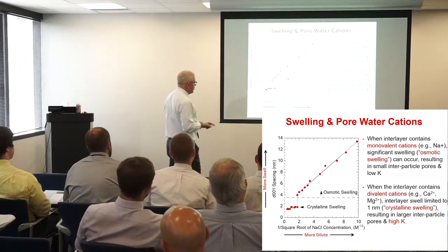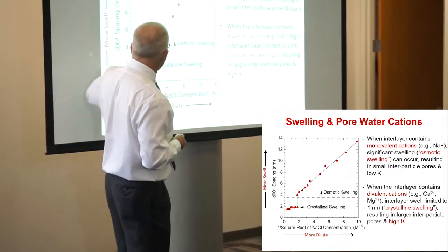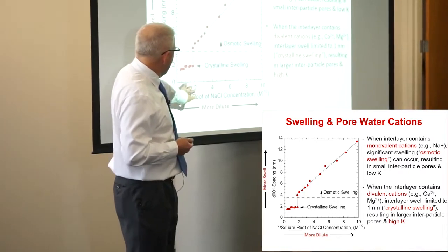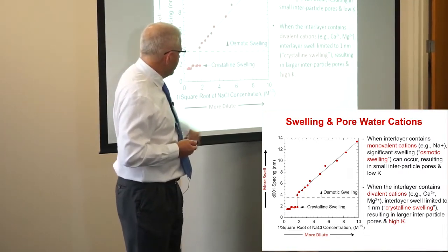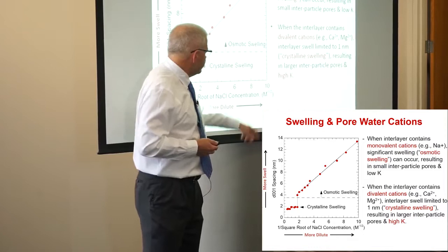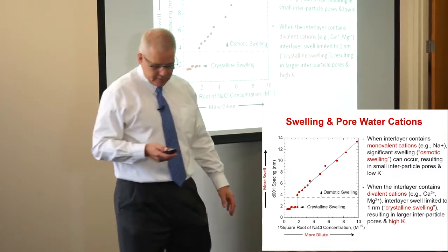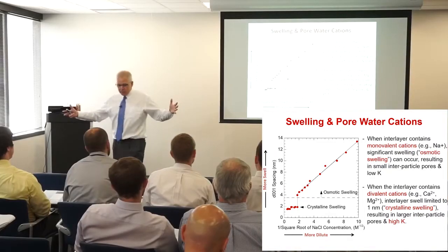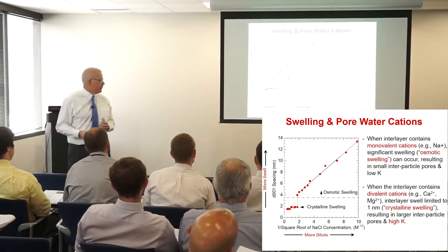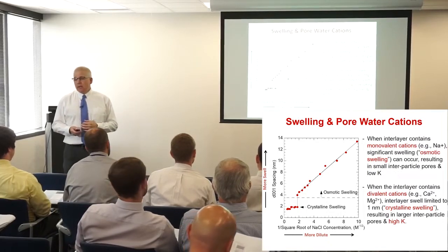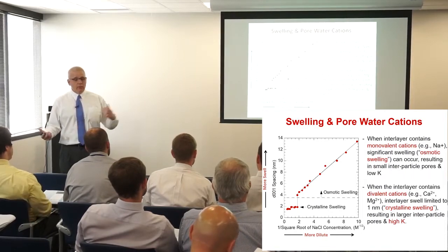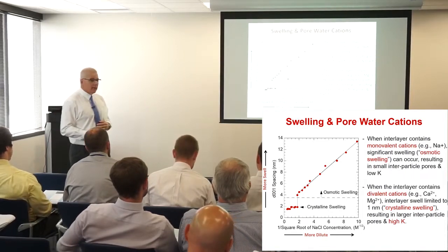The amount of osmotic swelling, as you can see in this graph, is a function of concentration. When we're in a very concentrated solution, we get essentially no osmotic swelling. When it's very dilute, we get a lot of osmotic swelling. So the amount of swelling that occurs depends a lot on the chemistry — concentrated solutions, it doesn't swell at all; dilute solutions, it swells a lot.